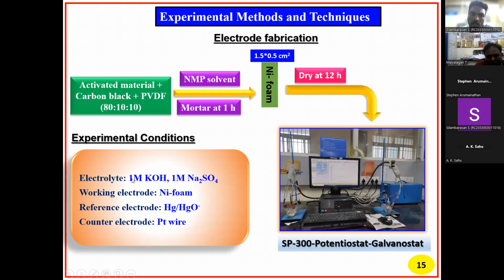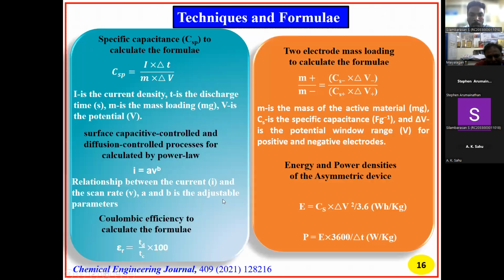For the experimental conditions, we used 1 mole KOH and 1 mole sodium sulfate as electrolytes, nickel foam as the working electrode, mercury and mercury oxide as the reference electrode, and platinum wire as the counter electrode.